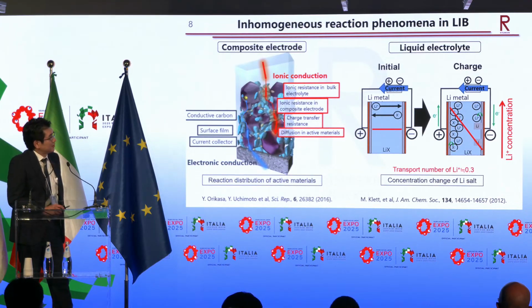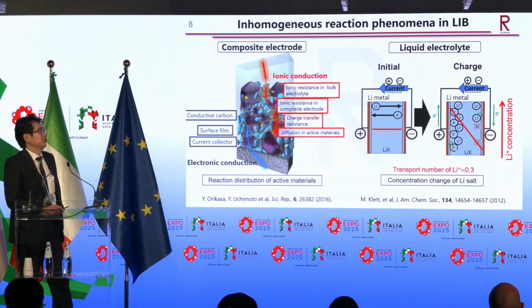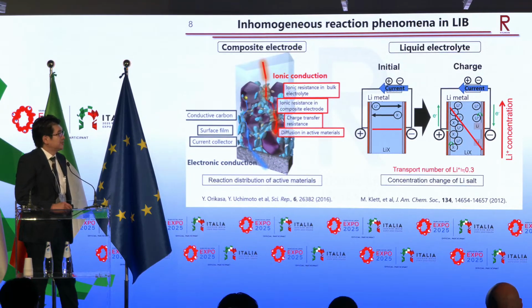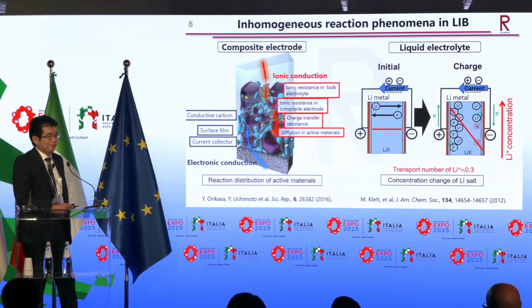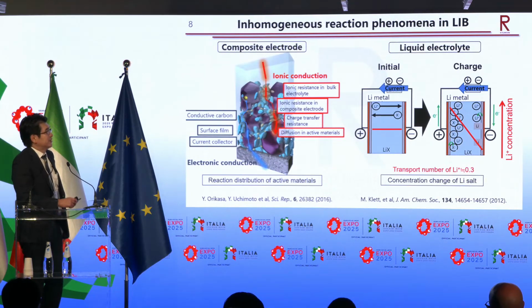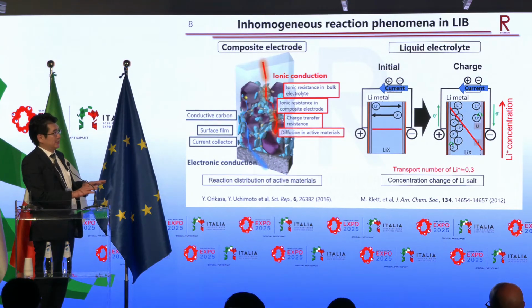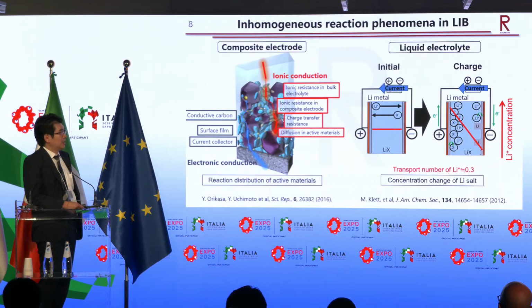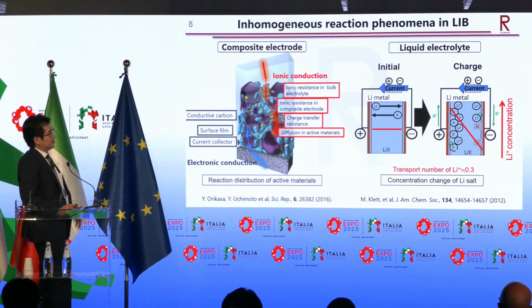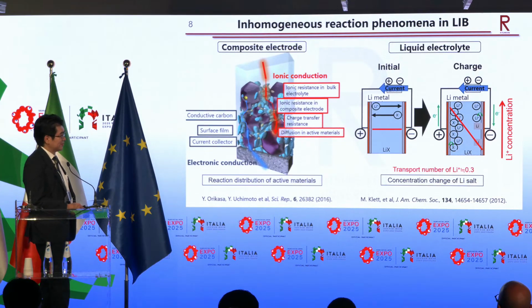The right side is concentration distribution due to mostly mass transfer behavior. So the transport number of the electrolyte used in lithium-ion battery is about 0.3. So for the initial state, the concentration is similar, but during charge discharge, the concentration of lithium-ion salt is not uniform. So we analyze the two types of inhomogeneous reaction of lithium-ion battery.